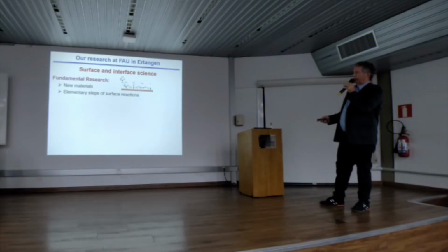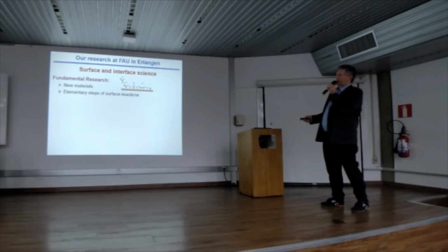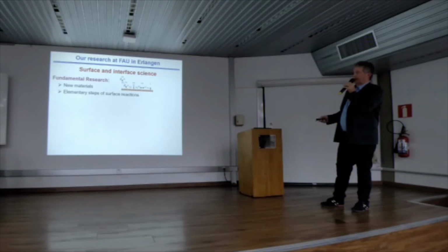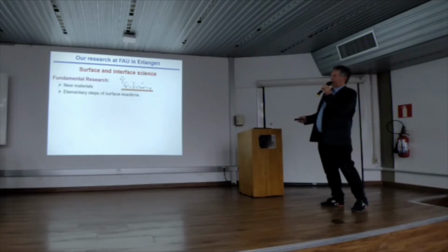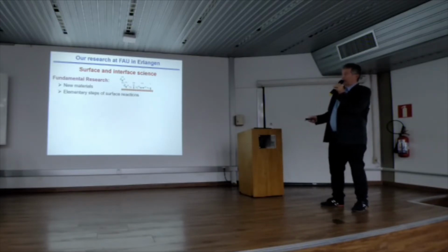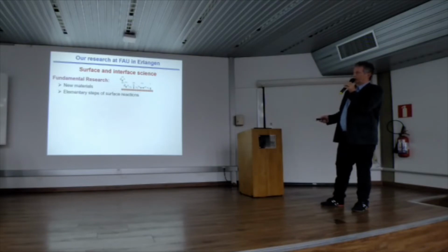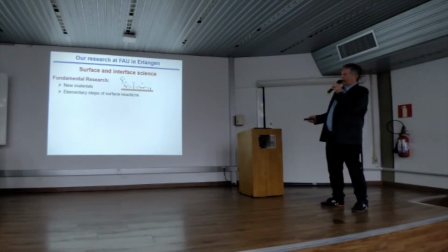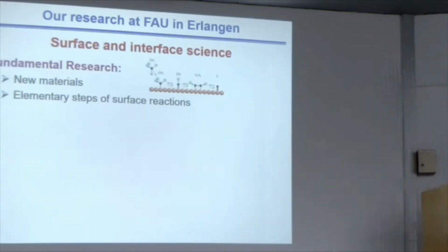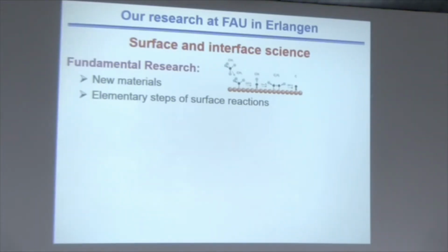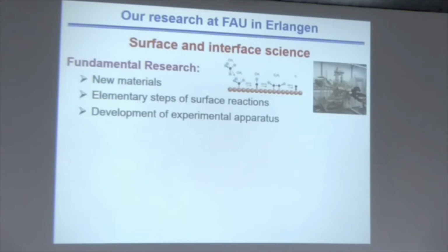So here you have a single crystal surface. You come in with methane. Methane is a very stable molecule, so if you want to adsorb it, chemically adsorb it, chemisorb it, you have to break one CH bond, which is very hard, and we try to find out what you can do to do that, and then we want to understand the following steps. And then if you do that long enough, you form molecules, decompose molecules, you end up with carbon, and if you do that long enough, you get graphene, if you do it right, at the right temperature, right conditions.